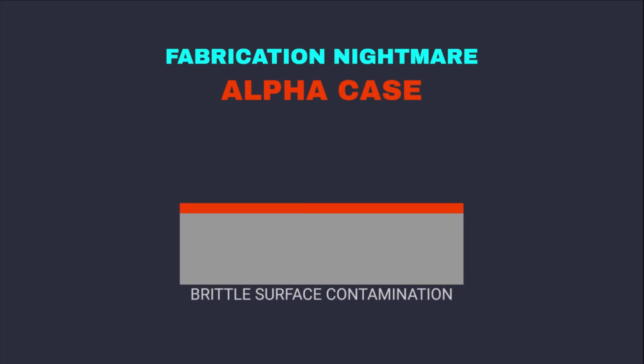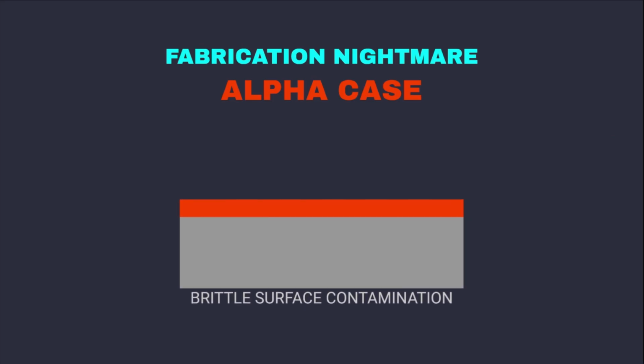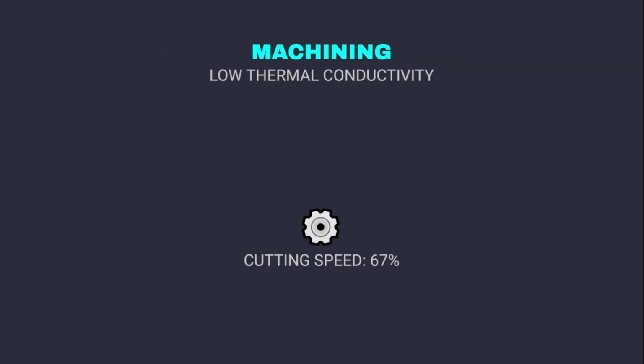Titanium reacts readily with oxygen and nitrogen at elevated temperatures, forming a brittle surface layer known as alpha case. This contamination severely reduces fatigue life and structural integrity. To mitigate this, all welding and hot forming operations had to be conducted in inert gas environments, typically using argon or helium chambers. Machining titanium is also difficult due to its low thermal conductivity, which concentrates heat at the cutting edge, leading to rapid tool wear and potential material damage. Specialized tooling and low cutting speeds were mandatory to maintain dimensional accuracy and surface finish integrity throughout the manufacturing process.